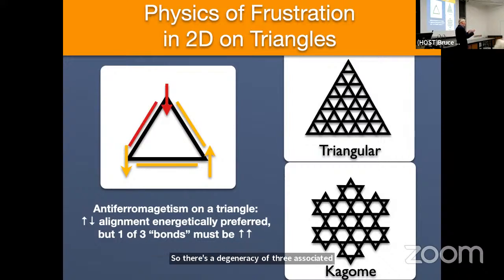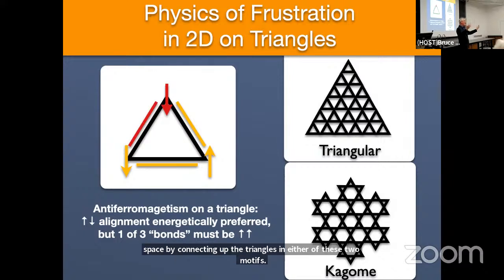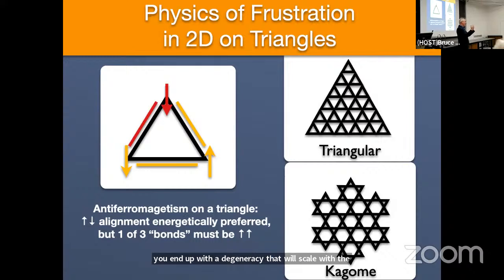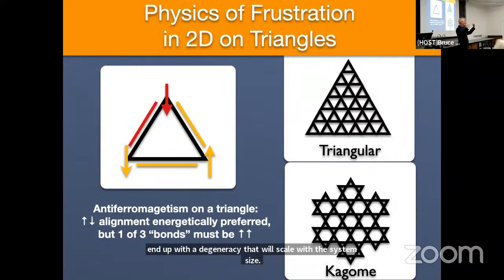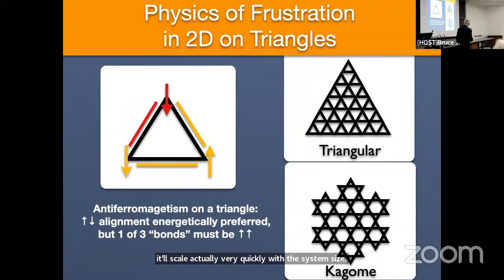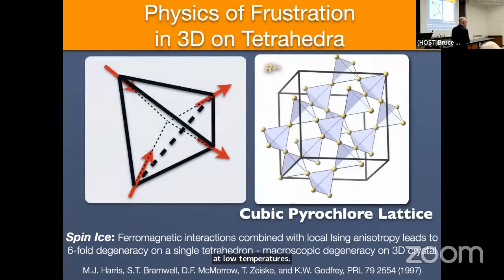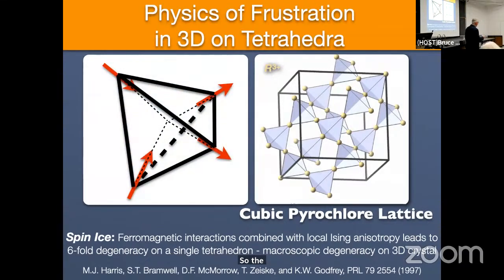And then if you tile two-dimensional space by connecting up the triangles in either of these two motifs, you end up with a degeneracy that will scale with the system size, okay? And it'll scale actually very quickly with the system size. And this will lead to what's referred to as an extensive degeneracy. And an extensive degeneracy is sufficient to generate enough entropy to preclude the formation of an ordered state at low temperatures, okay? So the tetrahedron is to 3 dimensions what a triangle is to 2 dimensions.